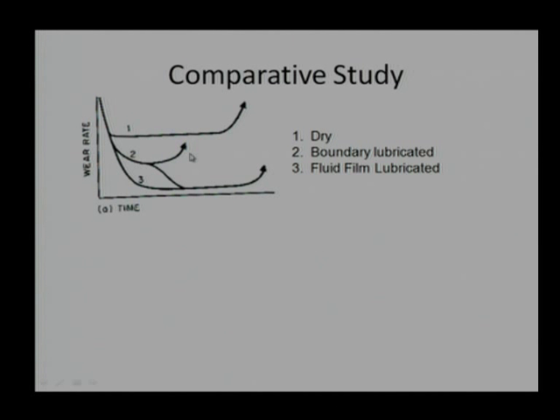Well, in the boundary case, anything is possible. Initially it is decreasing, it reaches one point, after that it can go and merge with one, or it can merge with three. That means if the surface roughness has decreased substantially, boundary lubrication may turn out to be a full film lubrication mechanism. Or if the surface is disturbed and irregularities have increased, it can go and merge with the dry case. Our boundary lubricant will not be effective in that case.